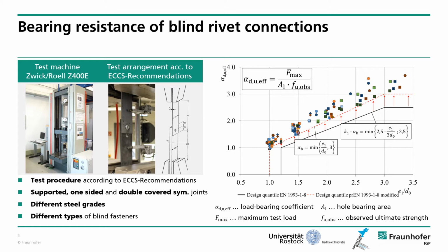The tested joints were one-sided supported and double-covered symmetrical joints, where we use different steel grades of the sheet materials. The steel grades were S235 up to S700. For joining this sheet material, we use different types of blind fasteners. For the evaluation of the test results, we use the load bearing coefficient, which is the result of the maximum test load, the hole bearing area, and the observed ultimate strength.